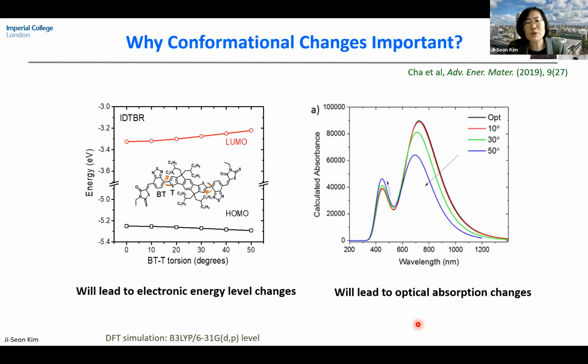This conformational or molecular structure change upon excitation is really important because it will change your electronic energy levels as well as optical properties. So even though you start with a very planar molecule, while you are exciting the molecule, it changes its conformation. Therefore, your HOMO and LUMO energy levels also change, at the same time reducing your absorption, particularly low energy CT state-like transitions.